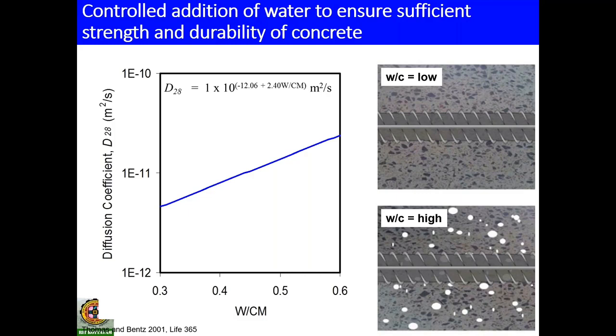When the water cement ratio is low, we will end up with a less permeable or less porous microstructure. If the water cement ratio is more, you will end up with a more porous system, and if these pores are connected, it is a free way for the deleterious agents to enter your system. So you should have control over the addition of water. What will happen if the workability is less? What should you do? You should use chemical admixtures. Don't increase the water cement ratio. Rather, use a good chemical admixture.